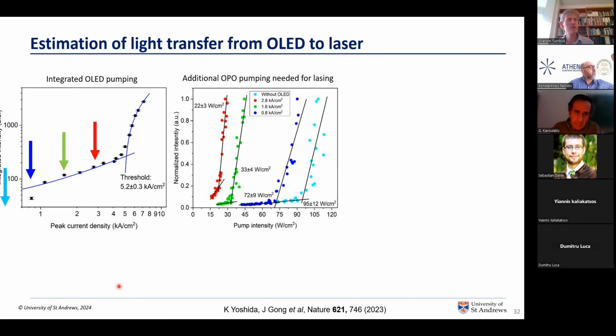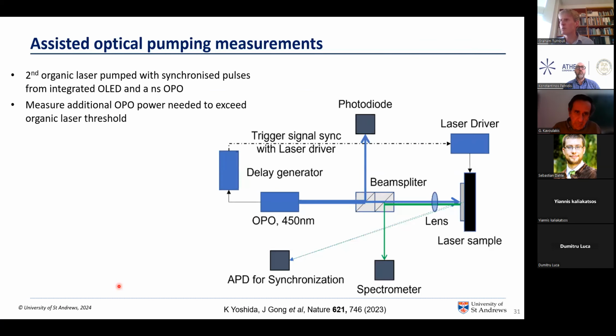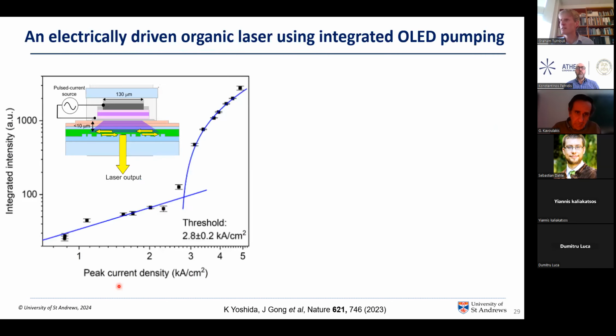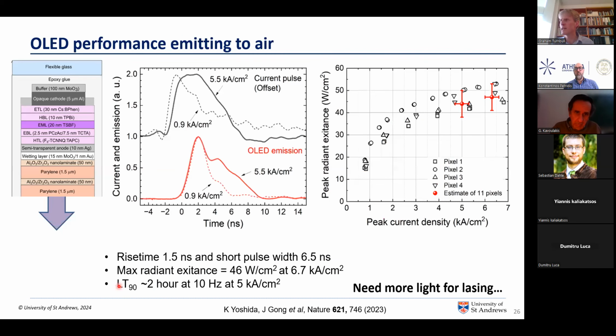The other thing that's limiting efficiency at the moment is that the OLEDs, I think I haven't got the right slide in this stack, but the OLEDs, the radiant excitance, so the watts per square centimeter coming out of the OLED as a function of current density going in, is significantly rolling off at these regimes, and that's partly because we've not yet optimized just the electronic properties of injecting these short pulses into the device.